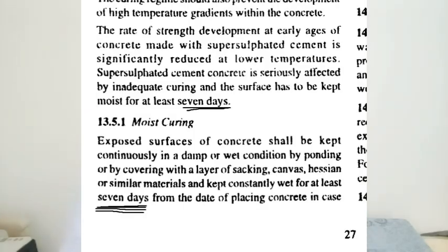On this page curing is properly described: if you are doing moist curing, and the surface of the concrete is exposed, then you need to do at least 7 days of curing from the date of placing of concrete. Okay, that is what is given in this.